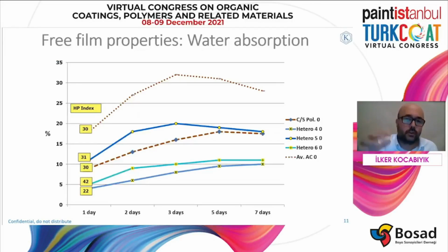In order to demonstrate this phenomenon, free film water absorption values of polymers with varying HB indexes were plotted in this graph. The red colored line on top represents an average straight morphology acrylic with an HB index of 30, for example, an MMA and BA composition. The second red line below represents another acrylic with heterogeneous morphology, also with the same HB index, but much lower water absorption values. This is a clear example of using the right polymerization technique by manipulating hydrophilic and hydrophobic domains in the core and in the shell. It is possible to achieve improved water resistance with the same monomer compositions.